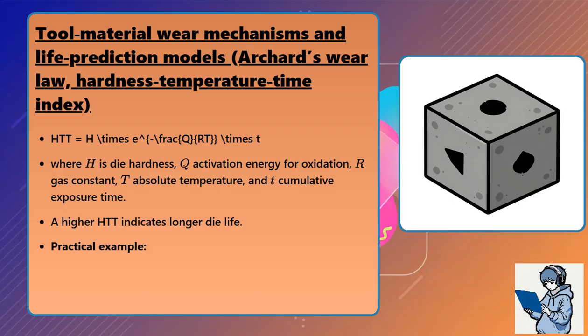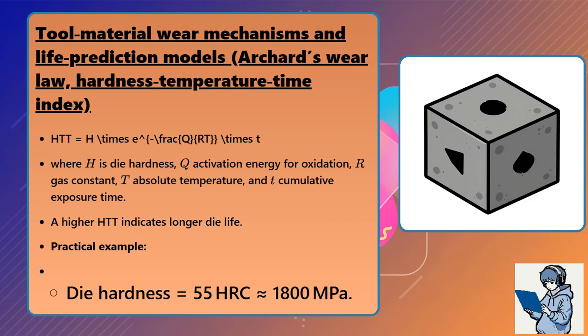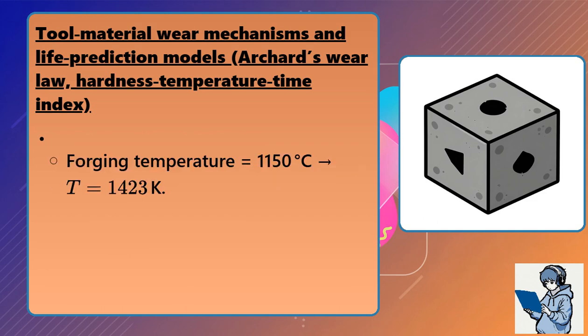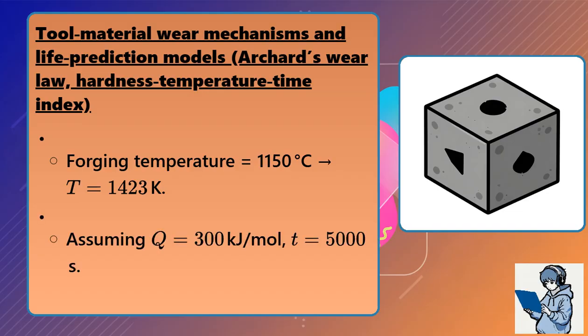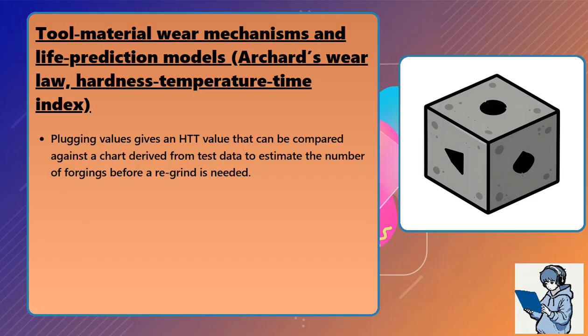Practical example: die hardness equals 55 HRC, approximately 1,800 megapascals. Forging temperature equals 1,150 degrees Celsius, which corresponds to T equals 1,423 Kelvin. Assuming Q equals 300 kilojoules per mole, t equals 5,000 seconds. Plugging in these values gives an HTT value that can be compared against a chart derived from test data to estimate the number of forgings before a regrind is needed.